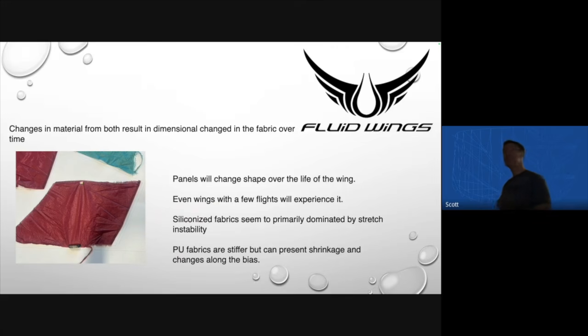Siliconized fabric seems to stretch primarily, right? And that's a behavior we see a lot. PU, polyurethane, is stiffer, but along the seam lines, we tend to, no, this is an important distinction. It's not the fabric panel as a whole, but along the seam lines, we tend to see a shrinkage. It presents as a shrinkage. So like an FT30 wing, if we were to try and put a new bottom seam on it, the seams don't quite line up as much.